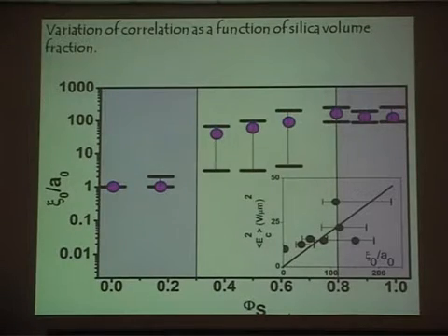experiment to experiment, my critical field also has an error bar. So it's difficult to a priori know when I have made a film where this film is exactly going to fail. Film to film it will change, even if it's by few percent. But that few percent reflects very strongly when I look at the creep behavior. So if I am within 1% of my electric field, then I get a different kind of creep behavior. When it's slightly less than that, I get a different kind of creep behavior. But we know that creep is a very important problem in all of this.